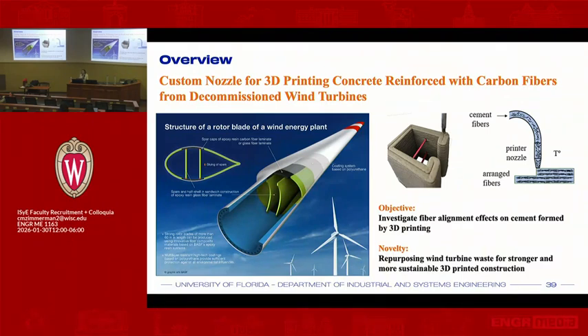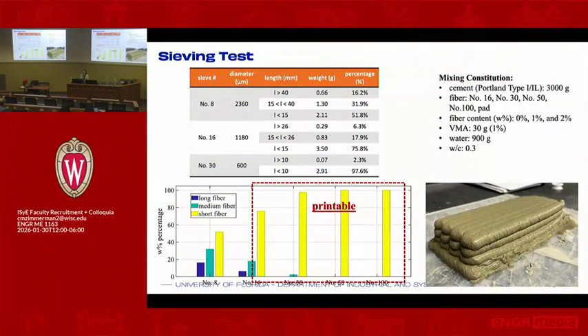So masonry is out there, and they do use composites, but how does it compare to a 3D printed one with an already used type of supply chain? Very local supply chain, I must say. So what happens? You probably saw that the problem is that those fibers are also going to cause the nozzle to get clogged up. So it's going to be an issue too. How do we actually control the strength, because we're going to need a certain level of fibers in the mixture, and we also don't want to stop the process to clean the nozzle every single time? And also we want to know whether we can actually get some directionality.